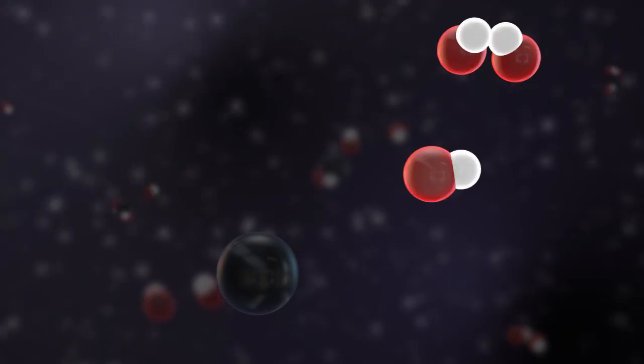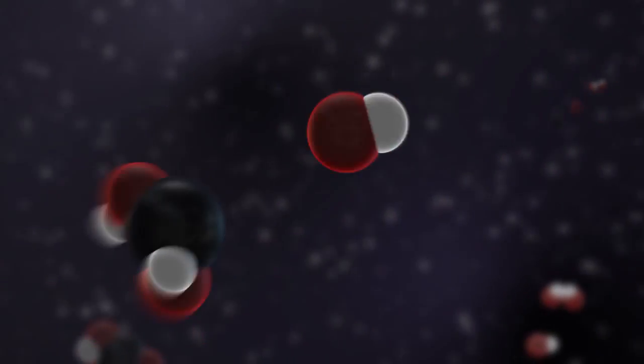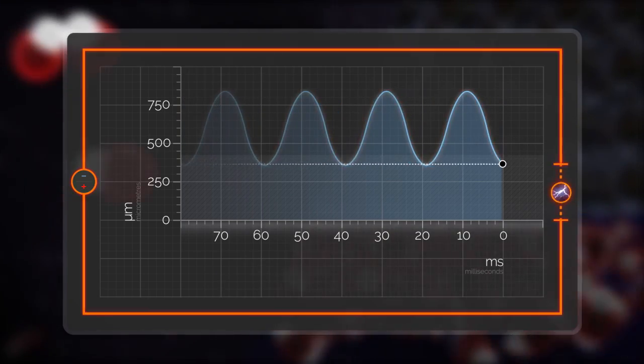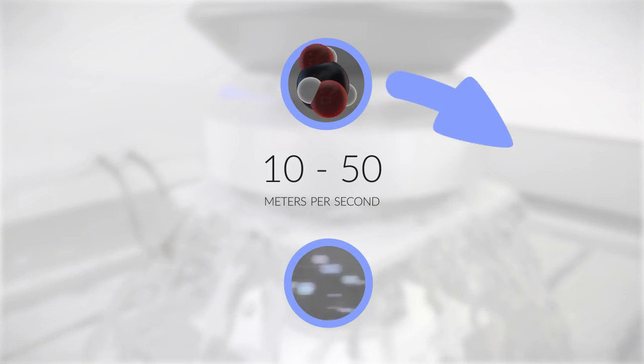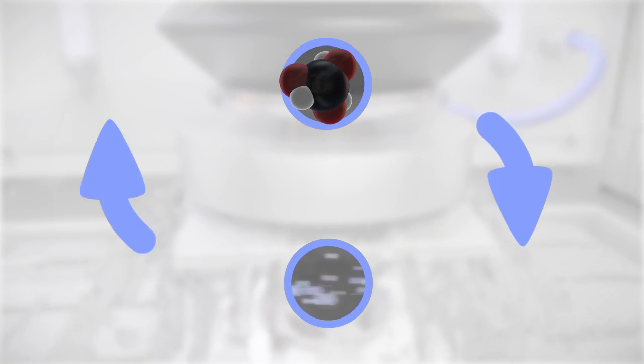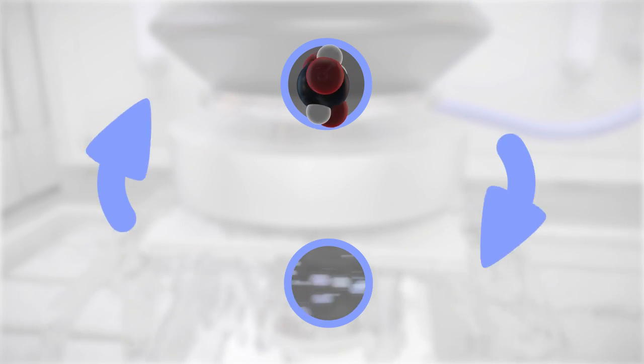The dissolved metal ions can combine with these hydroxyl ions to form metal hydroxide. These reaction products—metal ions, metal hydroxides, hydrogen gas, and heat—are transferred by the electrolyte at a speed varying between 10 and 50 meters per second. The electrolyte can be reused indefinitely due to the use of high-quality filtration and cleansing techniques.